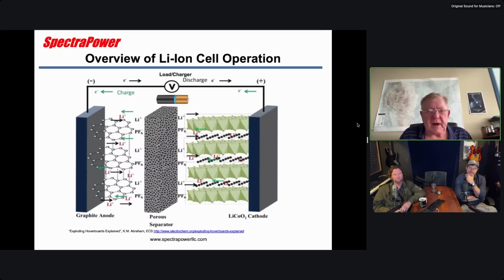Now, if you try and move them too fast by applying a lot of charge quickly, they bunch up. Think of it along the side here. They bunch up against the graphite particles, because they can't all get in at once. It's like the mob rushing to the door to get out. And they're both positive charges, so they're repelling each other. And so what happens is that it'll just stop charging because there's too much charge at one time. If you remove the charger, then sometimes you'll see it relax, and so the voltage will change.